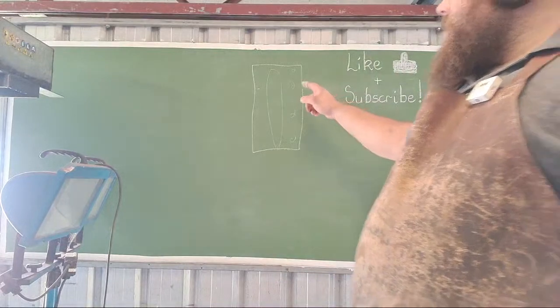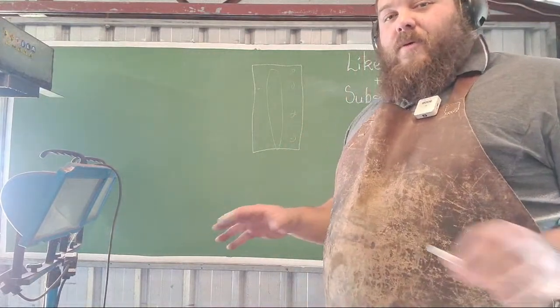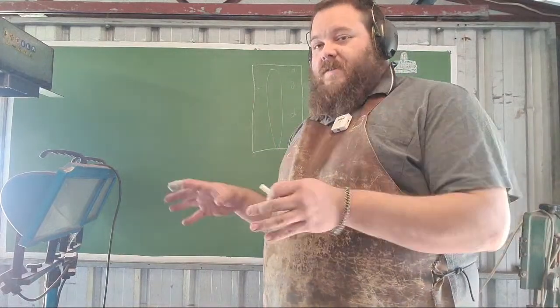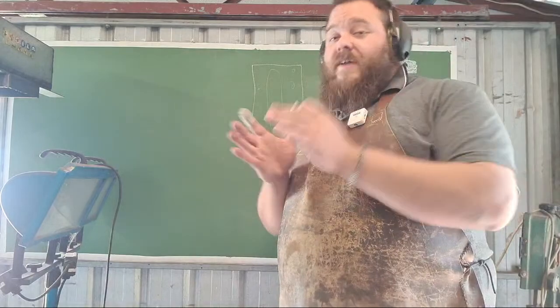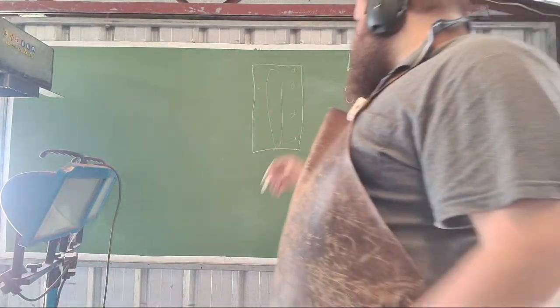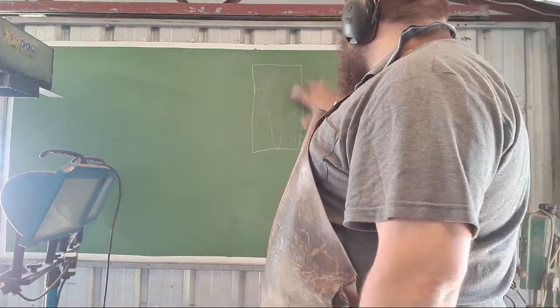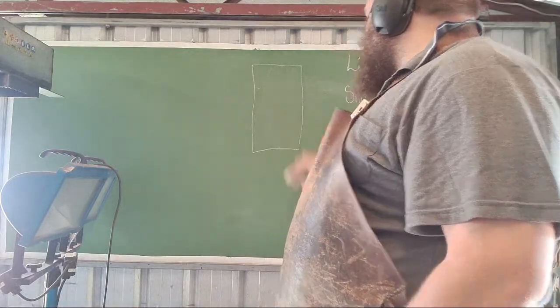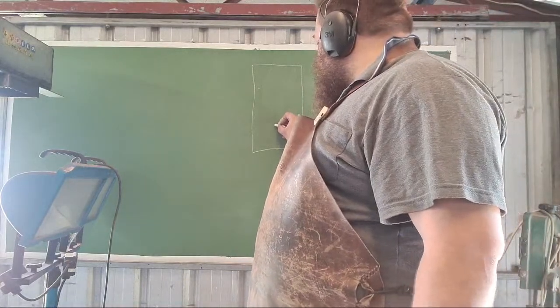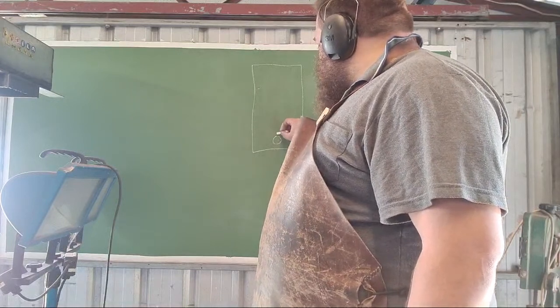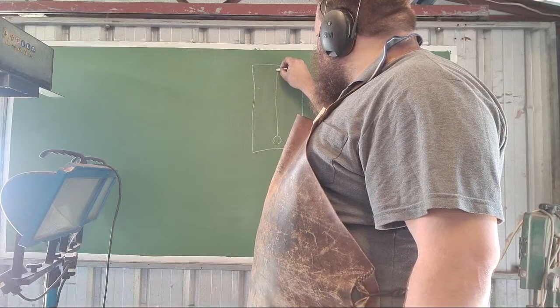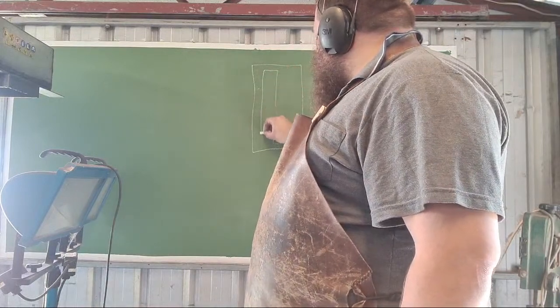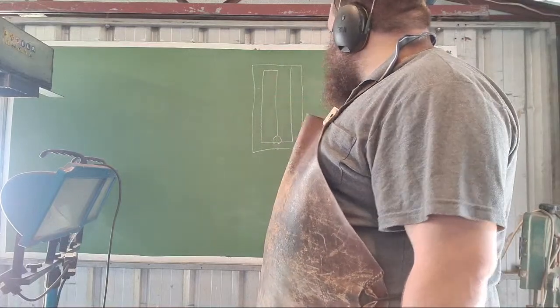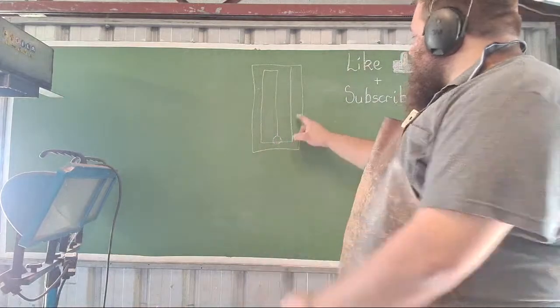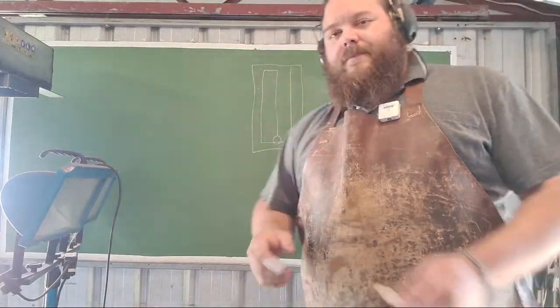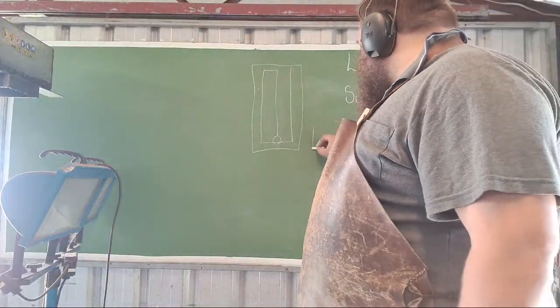And unfortunately, once borax is trapped, it cannot weld. Borax does not force welding. What it does is get rid of oxides. So if it's trapped, the borax will prevent the weld. So instead of going for the outsides first, you want to travel from about here at the rear. You want to hammer blow up to the top. Then you want to turn this way, down, across, and then up again. What that'll do is squish everything out to the sides as you come, and then you can weld the sides up.